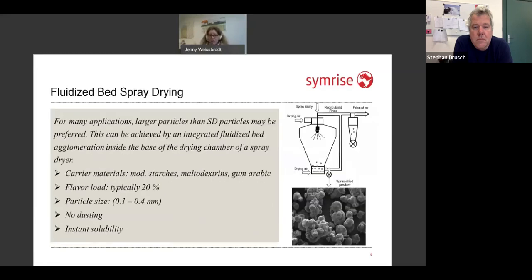To make particles bigger, a new process step has been introduced several years ago, and this is the fluidized bed spray drying. This means that a fluidized bed is introduced into the drying chamber at the bottom of the drying chamber, so that the particles are not directly harvested after they have dried, they are partly recirculated. The particles are more or less fed by the fluidized bed to a sifter system, where the fines are separated from the coarse material. The coarse material is what you get out as agglomerated powder. The fines are recirculated back to the very top of the spray drying tower.